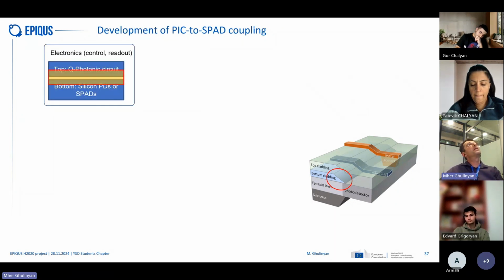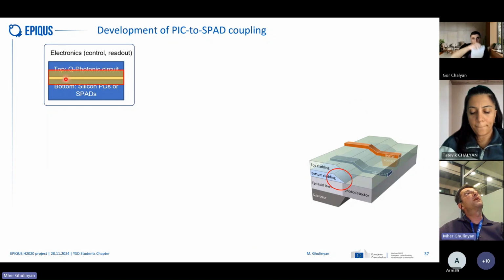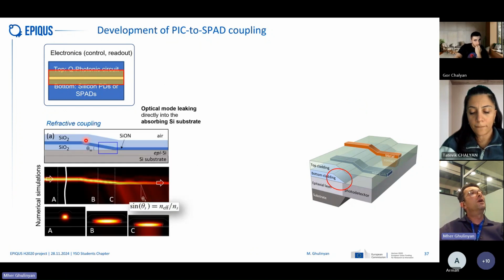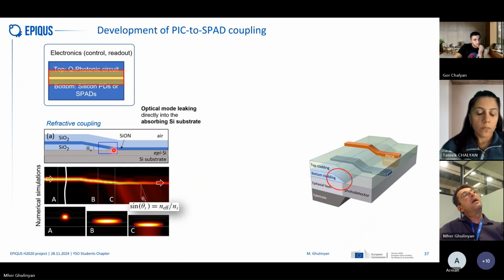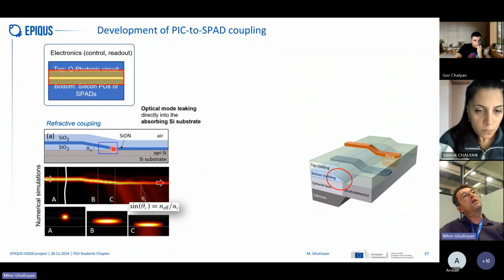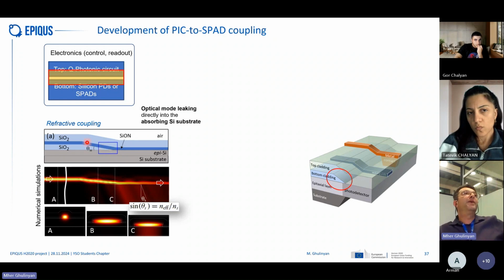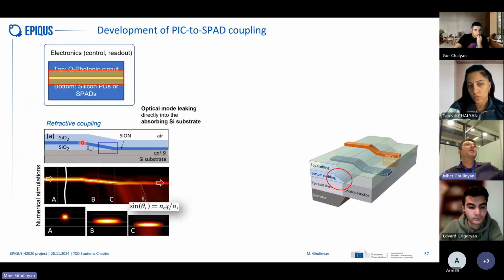Okay, so this is the schematic showing that at some point we need to make this coupling, but I wanted to show how this form of the waveguide can be created, because this has to be extremely smooth. With normal etching methods, which are dry plasma etching methods in microfabrication, you will create a very rough surface here in the SiO2 layer. So this is the cladding. And if this is very rough and your waveguide is then deposited on top, the single photon will be scattered out and lost before it reaches the detector. So this part has to be very, very smooth.